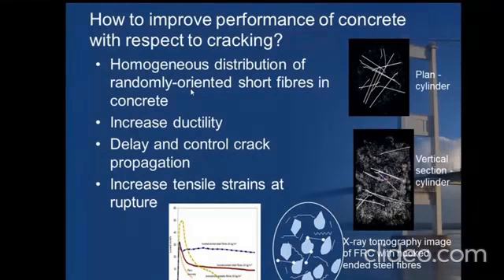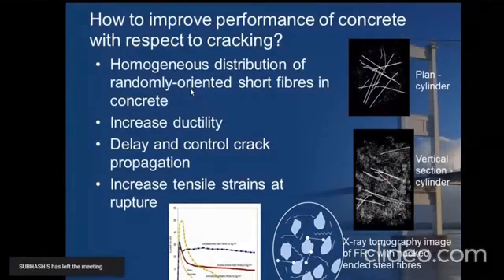Actually, it acts like a rubber band. These steel fibers in the matrix act like a rubber band, which prevents the widening of the cracks in concrete. And one more thing I would like to emphasize here is the major problem we come across in steel fiber is the quantity of fibers that get into the matrix. So we usually express it in terms of volume. Generally, we use 2% by volume and up to a maximum of 10%.